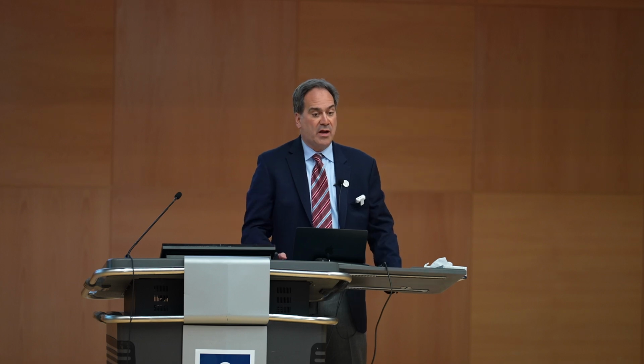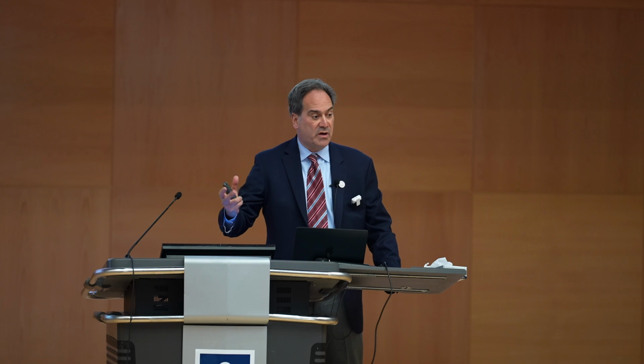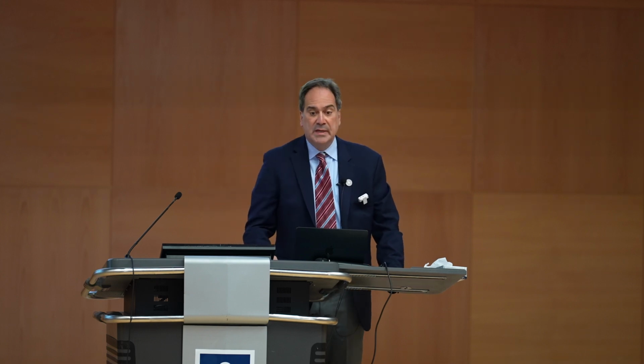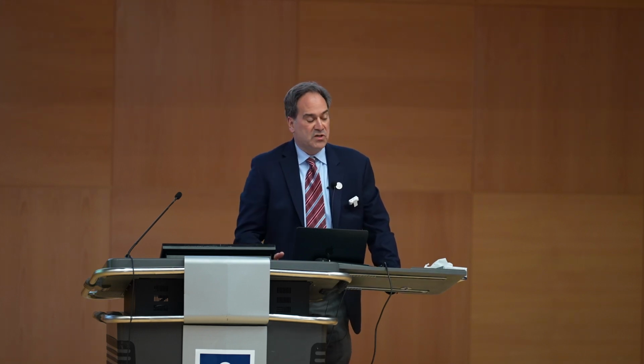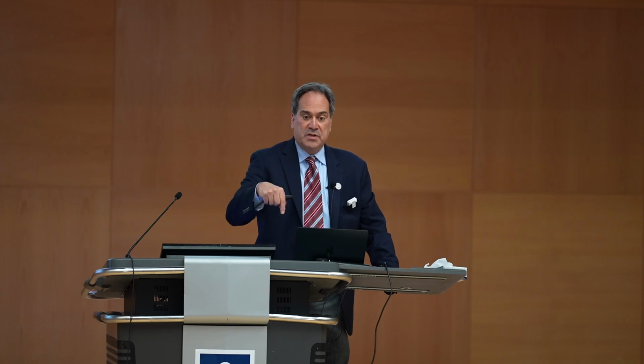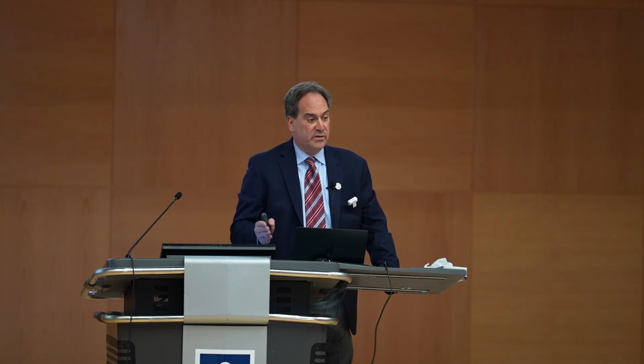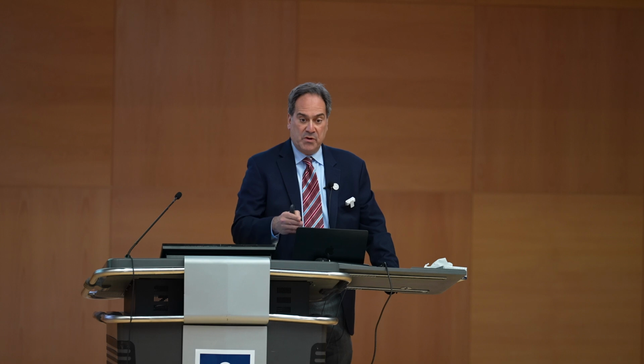Those are alkane thiol features made on gold substrates. So alkane thiols are the inks, the substrate or the paper in this case is gold. Thiol reacting with the gold is the driving force. The longer you hold the tip in contact, the bigger the feature you get. So you could control on the nanoscale both composition and also feature size.